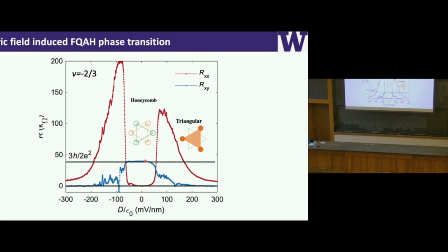As I increase the electric field, now you will see that RxX will increase dramatically, changing from 0 to about a few hundred kiloohms, with RxY actually nearly vanishing. So that represents a charge ordered state, likely to be a generalized Wigner crystal state. And at the larger electric field, RxX drops again with vanishing RxY. So that's some kind of metallic state. This shows you that we can actually tune this electric field to realize these topological phase transitions from this FCI state to some kind of a charge order, but topologically trivial state.